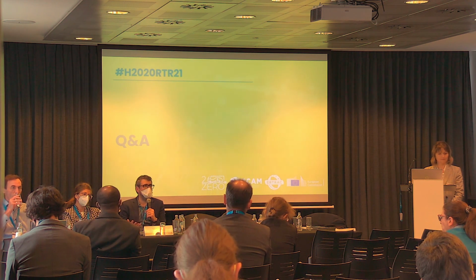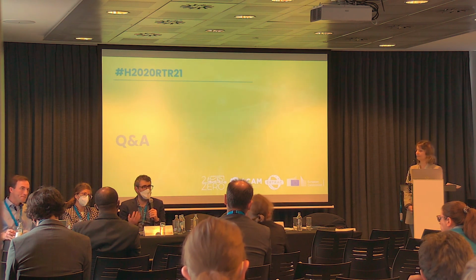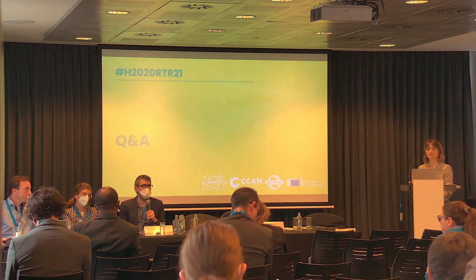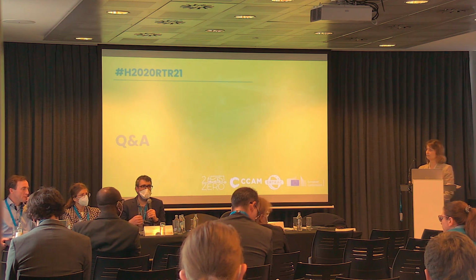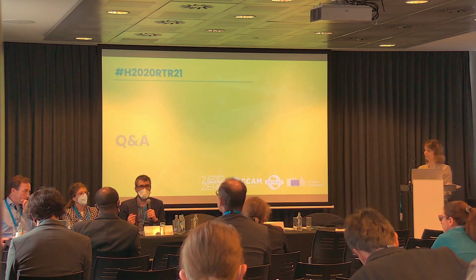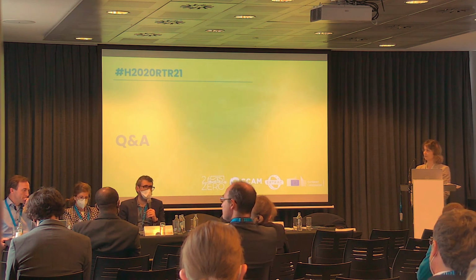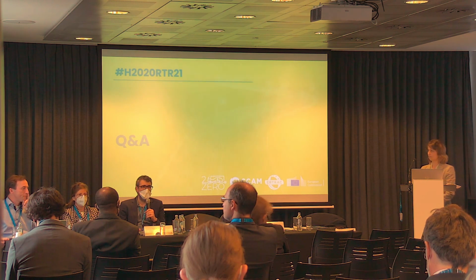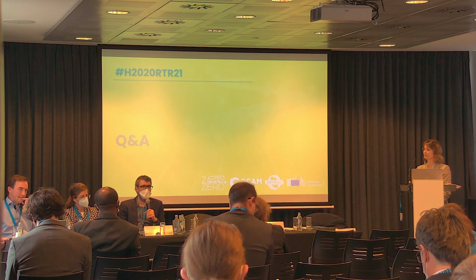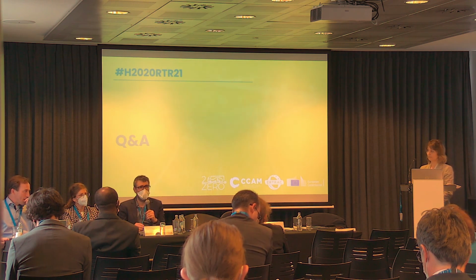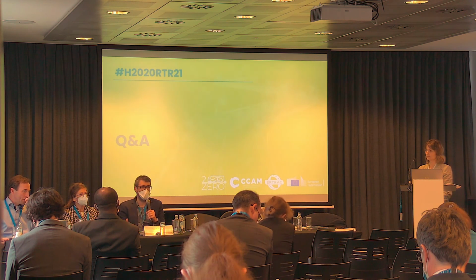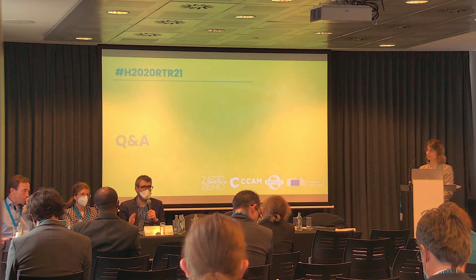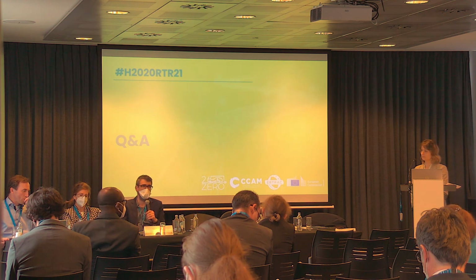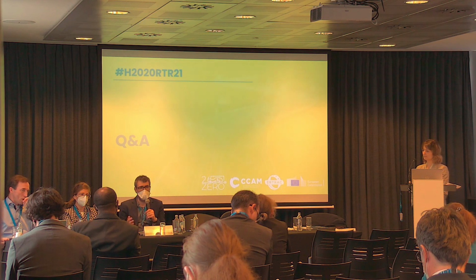So that's the point of the modeling, to predict such behavior, to say, okay, we have a new idea, we want to assess the benefits of a high loading electrode. Does it have a real benefit in the beginning? Does it still behave well after aging and so on? That's an important point to be taken into account, of course. And also for all solid-state batteries, we saw yesterday, for instance, many techniques with separated electrolytes. I asked these questions, and I think modeling can also be of help here to know whether it's a good point to have two electrolytes for the positive and the negative, or where to put the interface between the two electrolytes, at the negative interface or at the positive interface. It can be taken into account, and it's a good point for the modeling part, in the prototyping phase at least.